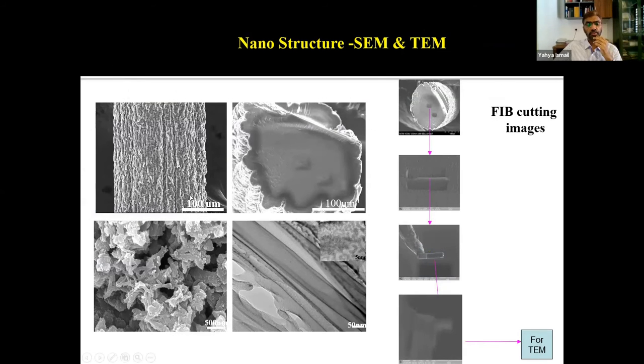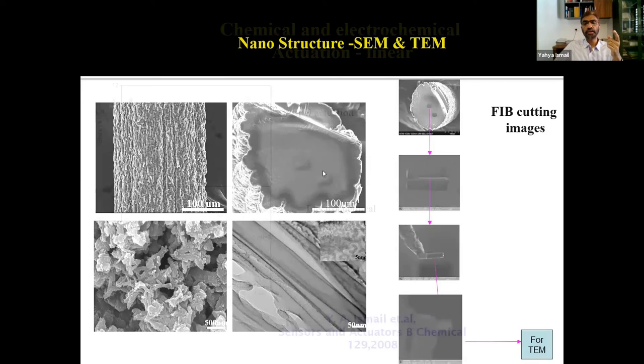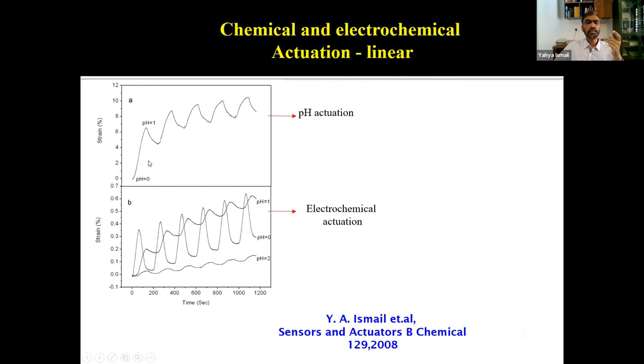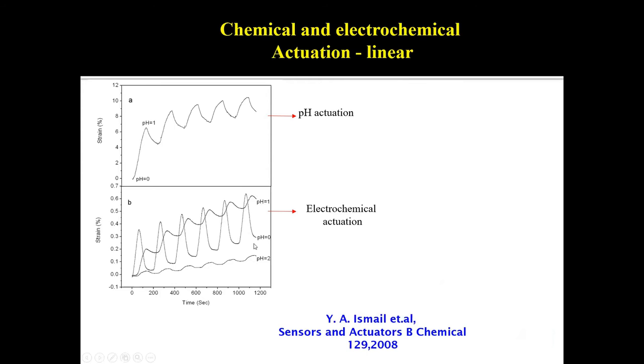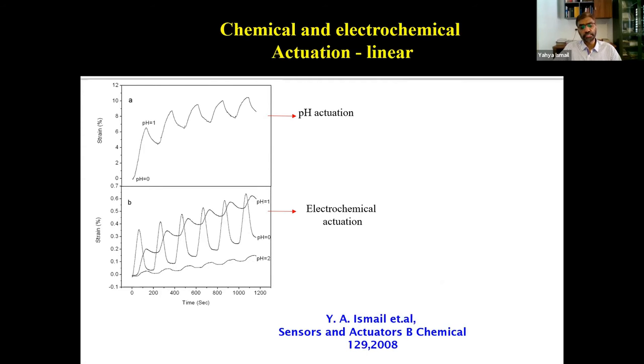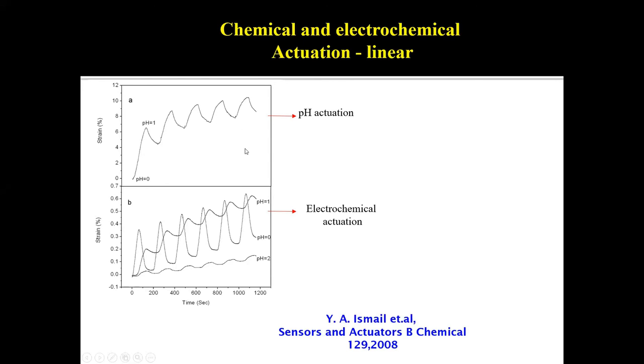So this is the example of a chitosan microfiber coated with polyaniline. The surface has a high porosity, enabling efficient diffusion of ions, and inside the hydrogel you also have polymer chain grown, which we studied through TEM. After applying the electrochemical potential, the electrochemical actuation strain we observed is around 0.4%. At the same time, if you switch the pH, we were able to produce chemical actuation, with an average strain of up to 4 or 5%, between 4 and 5% strain we received.